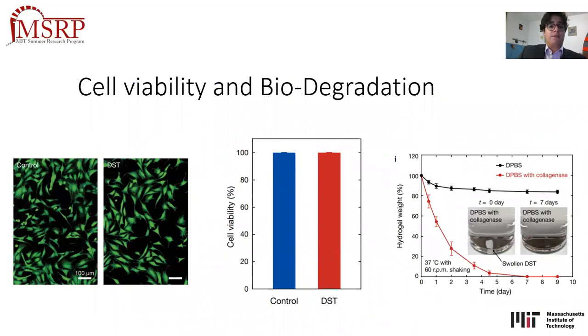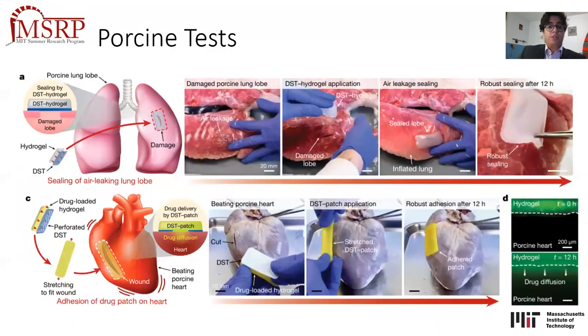Embryonic fibroblasts were used to study biodegradation and cell viability at 37 degrees Celsius, being a well-established model for cell growth. In vitro studies showed no observable decrease in cell viability. Additionally, the biopolymer had the ability to be degraded by endogenous enzymes like collagenase, lysozyme, and DNase at varying rates. Force tests were carried out to determine tissue adherence in open wound models.